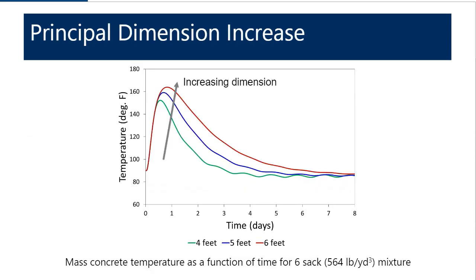So here's an example of how the dimensions of an element might increase concrete placement temperature. So for example, the mass concrete here is shown for an element that is increasing from 4 feet, which is the green curve, to 5 feet, blue curve, to 6 feet, which is the red curve. This is a single concrete mixture. And you can see that as the dimension increases, the maximum temperature of the concrete is also increasing.